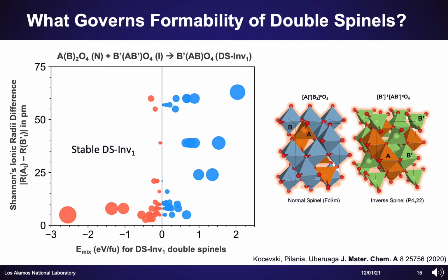Next, we focus on understanding physical factors that dictate whether a double spinel chemistry formed by combining two single spinels is likely to adopt an inverse or a normal double spinel configuration. We start by exploring simple correlations between various elementary features of the different elements forming the double spinel with the DFT calculated energetics. This exploratory analysis provided strong indications that local coordination environment dependent relative size effects of different cations going from single to double spinels play an important role in the stabilization of the double spinels.